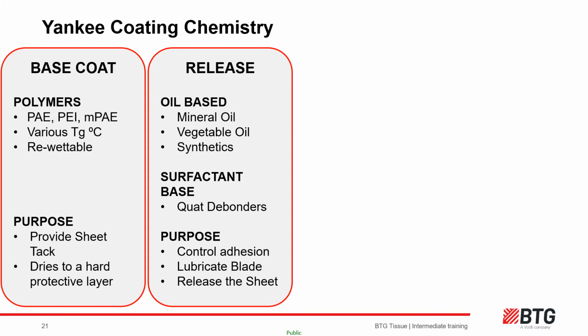Many release products are oil-based. Mineral oils are becoming less popular due to environmental profile, but generally give very good stretch response. Vegetable oils and synthetic derivatives are becoming more popular, although the release effect can be finite per product, pending other conditions and of course the base coat it's in use. Quat-based debonder type products are also popular. These can give very good release, soften the coating a lot, and also transfer to the sheet, providing surface softness.